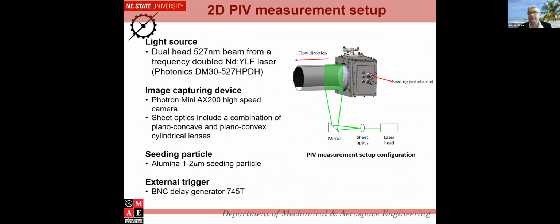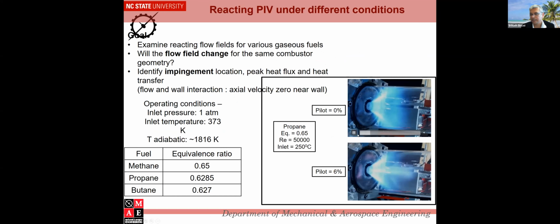So quickly, there's more. So I'm going to show you. This is all background again. How do we do PIV? This is in high temperature. Many of you know what PIV is. We use a high-speed camera. We have a dual head 527 nanometer beam, which we use to produce laser pulses, and then we seed with alumina particles. And you can see the images here.